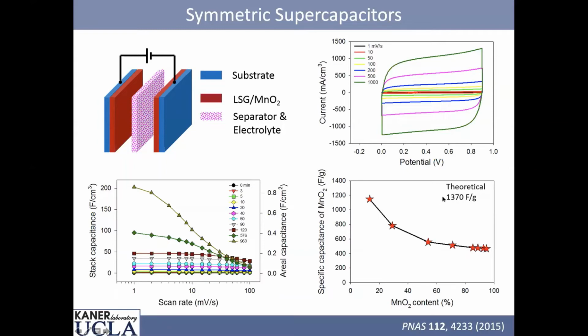But what's much more important is if we go the other way. If we go to 5% graphene and 95% MnO2, we're still at about 500 farads per gram. And that's the beauty of graphene. It doesn't take very much. You can use it as a scaffold and you can put other materials in. MnO2 is one. There are many other metal oxides that are even better than MnO2, and you can put any of them in that you like. But this is a good proof of principle.